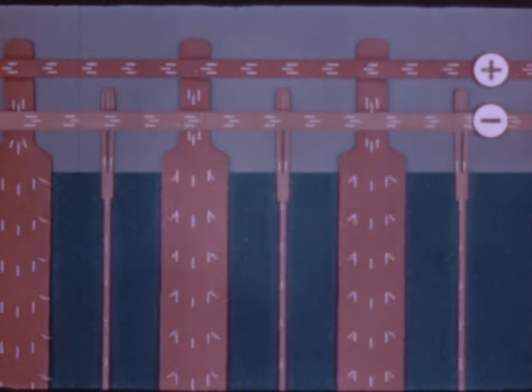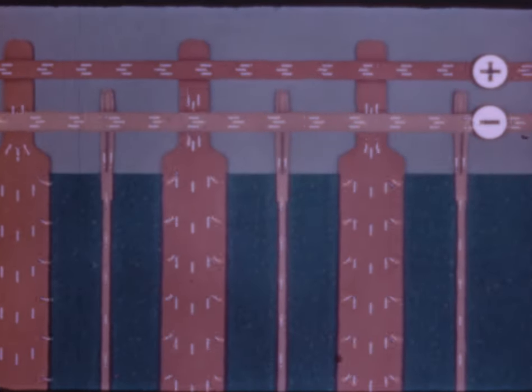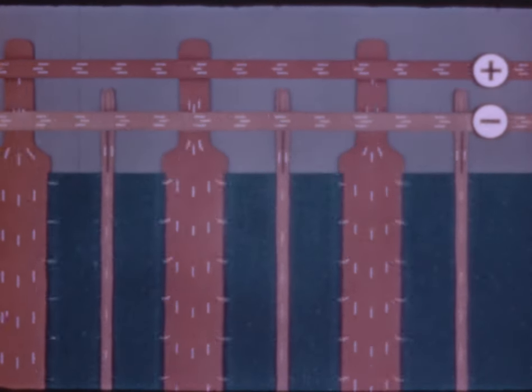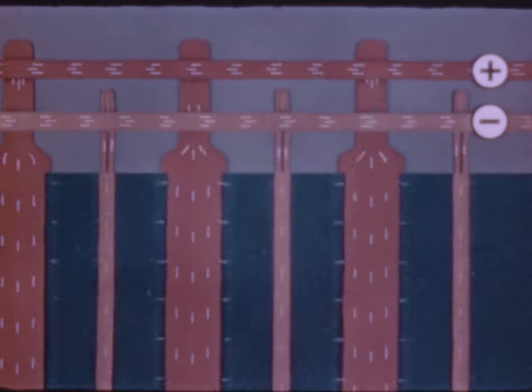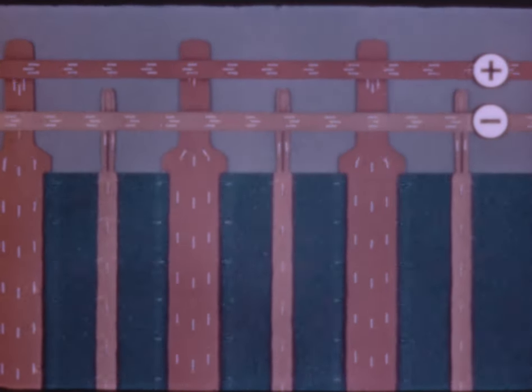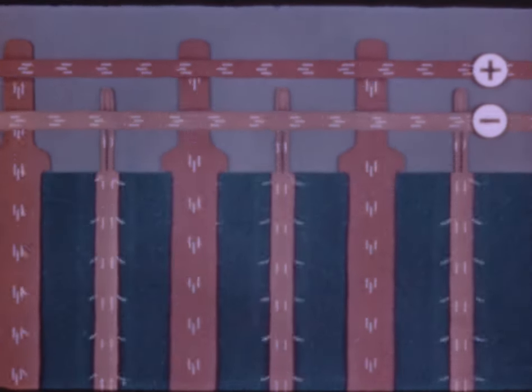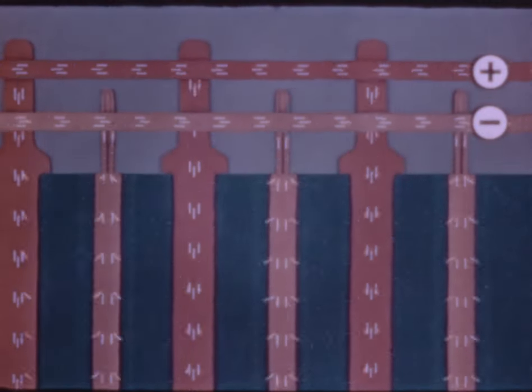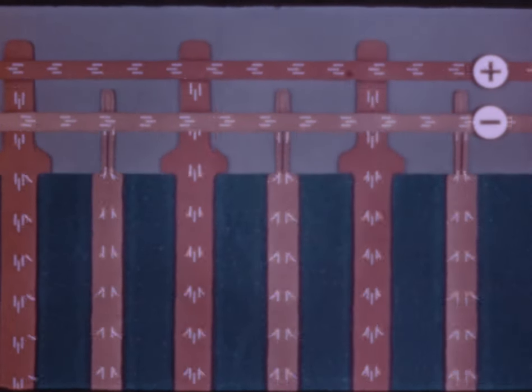Current flowing through the solution transfers pure copper from the anode to the cathode. In about 2 weeks' time, the 7-pound cathodes are built up to 175 pounds in weight, leaving impurities behind as a sludge, which is recovered and treated to reclaim the silver, gold, and other elements.